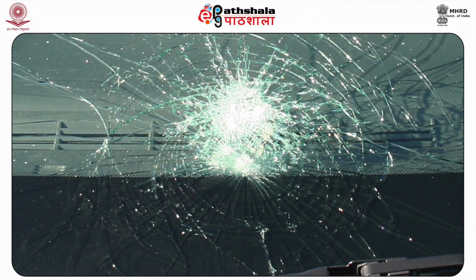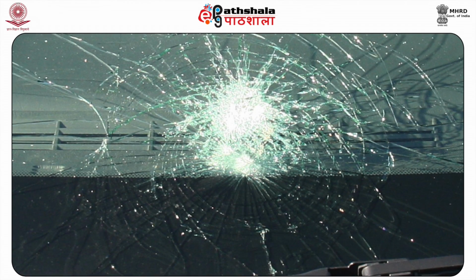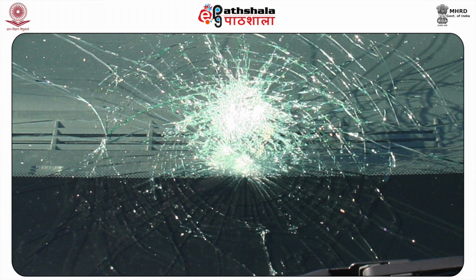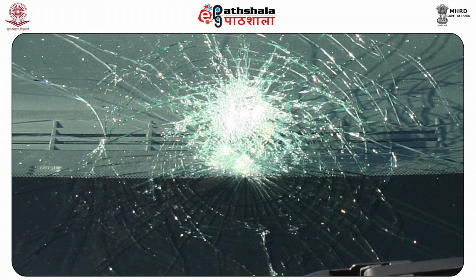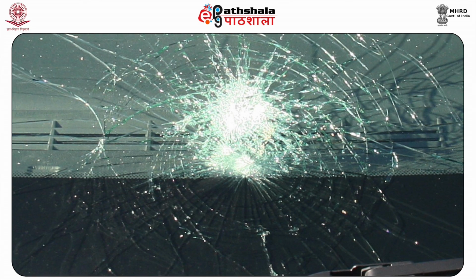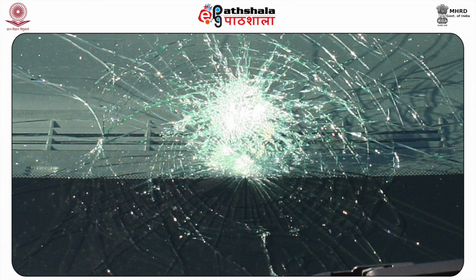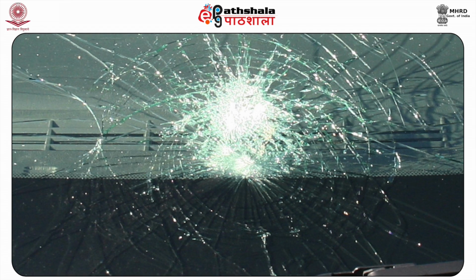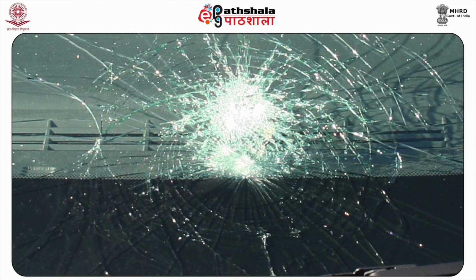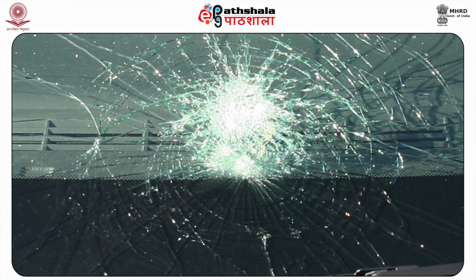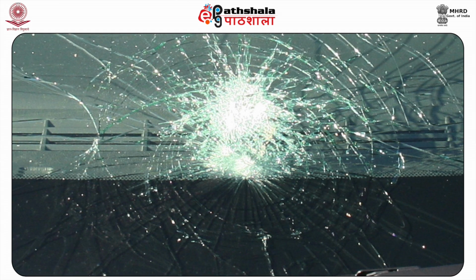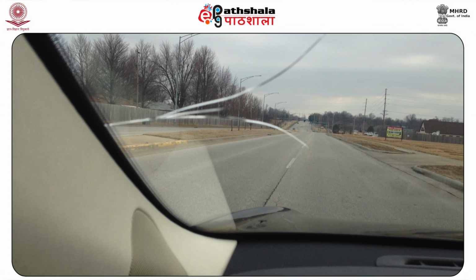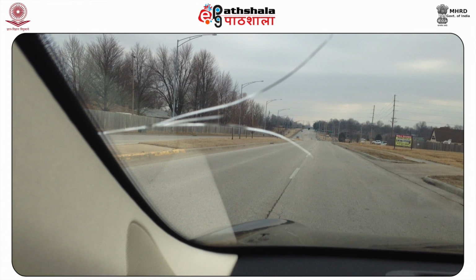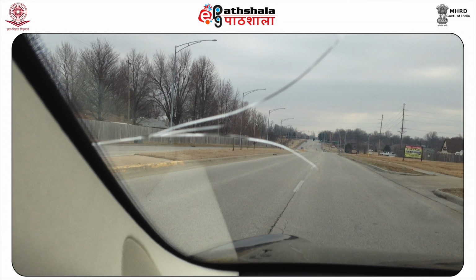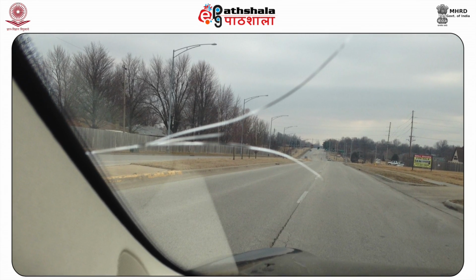In non-tempered glass, a typical heat crack is curved, has a smooth edge, and has no indication of the point of origin of the crack. Localized heating of thick pieces of glass can cause cracks with a feathered appearance. The side to which the heat was applied cannot be determined from fractured edges.